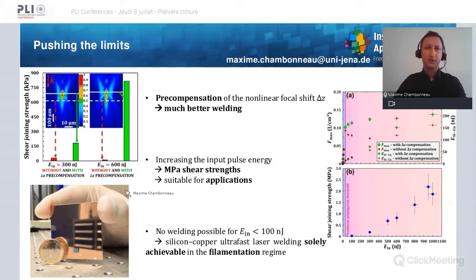Okay, let's try to push the limits a little bit. Here on the left, you can see the shear joining strength for two different input pulse energies, without in red and with in green delta Z precompensation. The striking feature here is that precompensating the nonlinear focal shift delta Z leads to a much better welding. So what now if we keep this delta Z precompensation strategy, but at the same time increase the input pulse energy? Well, the results are shown here in blue, where you can see that it is possible to reach around 2 megapascal for input pulse energies near 1 microjoule. And this is suitable for applications, as illustrated here on the left.